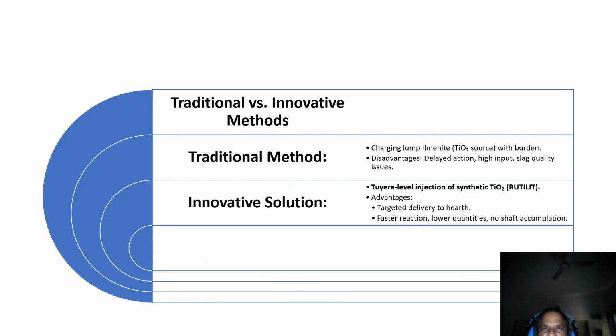Previously, TiO2 from ilmenite was added with the solid charge, which was slow to react and not very efficient. But now they use an innovative approach, that is injecting synthetic TiO2 directly through the tuyeres. This heats the hearth area more directly, reducing material use and avoiding problems with slag quality.